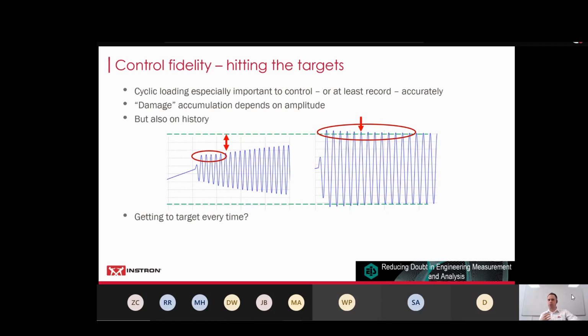Arguably worse, when we talk about those loading history effects, is if you've ended up a bit aggressive and you actually go over what you meant to, and you overshoot your target on the first few cycles. With fatigue, particularly if you're doing aggressive loading intentionally, if you overshoot further, it can really affect the fatigue life of the specimen. It can affect the work hardening. So when you talk about control, you want to know, are you getting to the target every time?